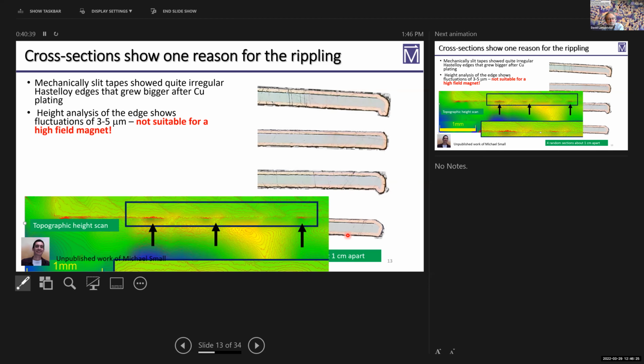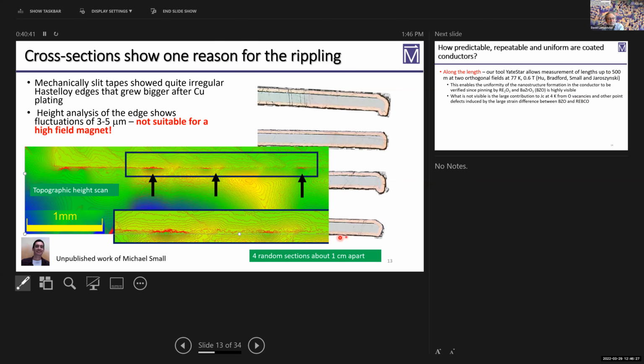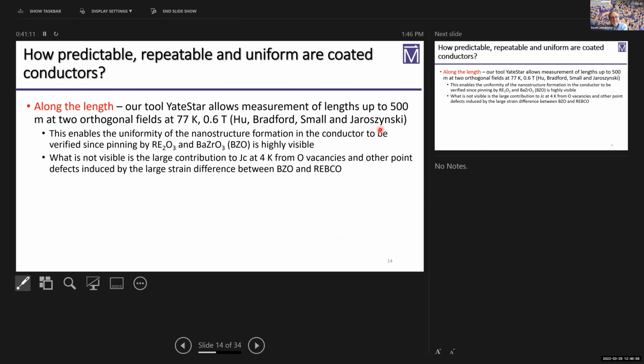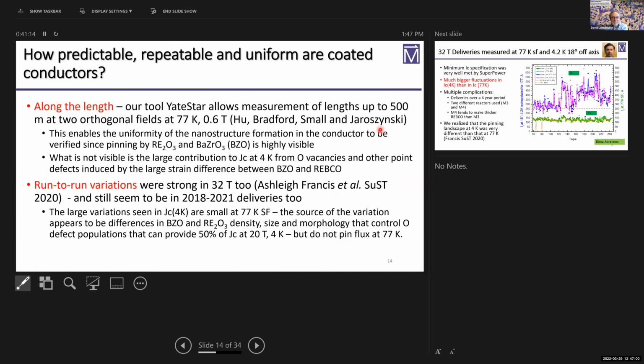But these are topographic height scans. So here is the edge of the conductor, and you can see that there are all these red hot spots which correspond to this thing. Well, now imagine you're winding a pancake out of these, and so these are all tight up against one another. There are very high stresses anyway in this situation. So you get very highly localized stresses as well under these circumstances. So you have to worry about things like this.